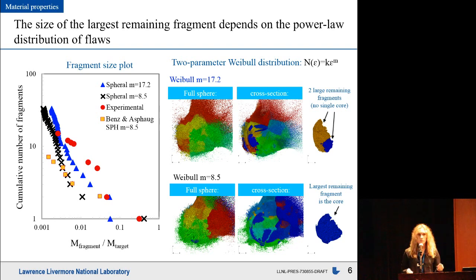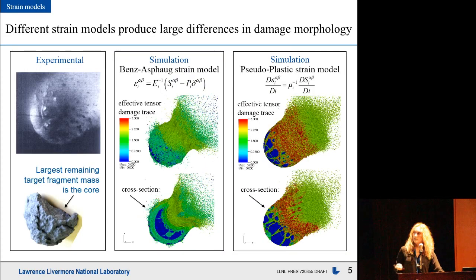When we used the exponent M equal 8.5 in spheral, we found a plane to look at this cross-section, and we were able to find the largest remaining fragment, this core here, which actually looks very much like the experiment itself. It's a very good match.